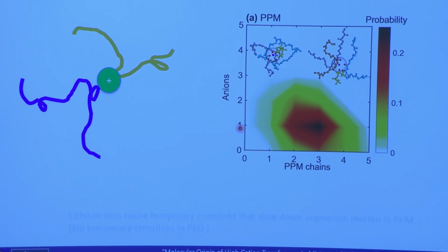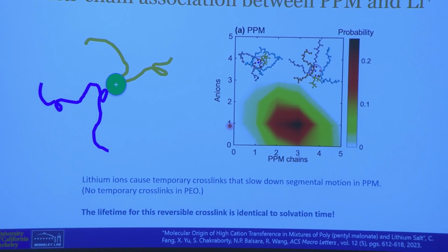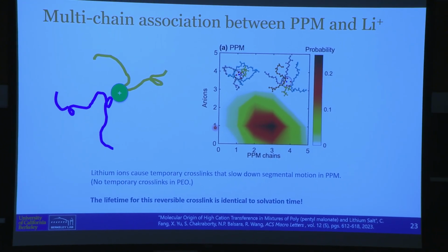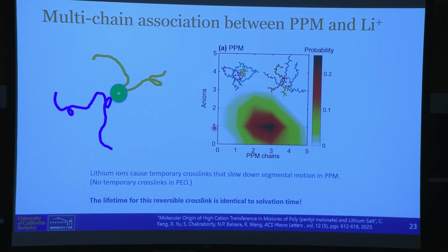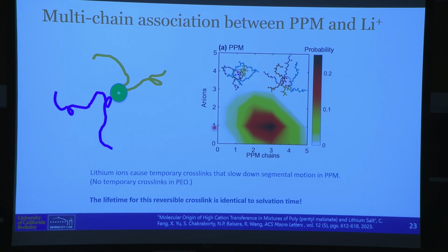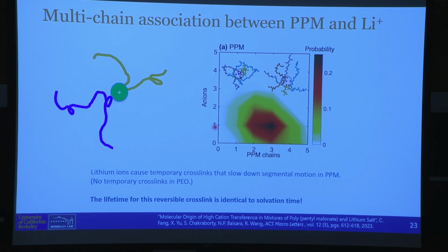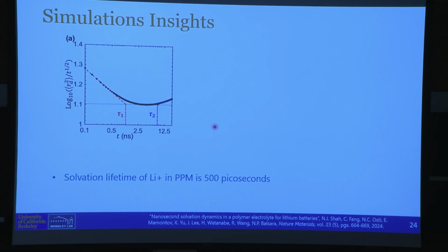And that is interesting because this lithium ion is serving as a temporary crosslink, a little bit like a hydrogen bond or something. And there is a rich literature on weak bonding between or temporary crosslinks in polymers. And what we are proposing is that this well-defined signature of a temporary crosslink lifetime is identical to a solvation lifetime. And so what we have proposed to the community is that you can use QENS to get solvation lifetime, provided it's not like PEO and everything is solvated just by 1 chain.